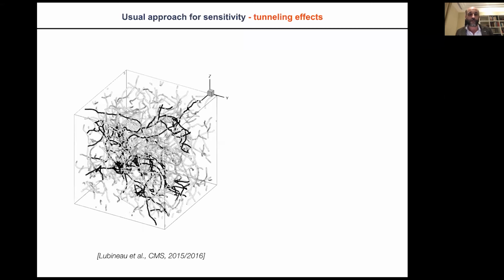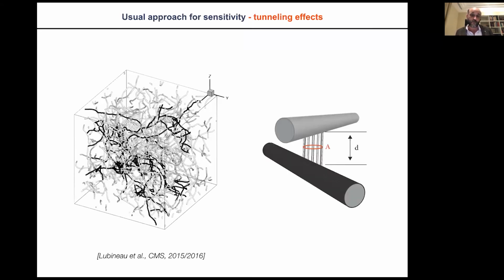So what you see in black here is a simulation of the percolated network of nanoparticles in a loaded polymer. It's impressive to see how many particles, in fact, are useless to the electrical signal, because all the white particles are not connected to the percolated clusters, so they don't conduct anything. The black skeleton here is the conducting network, and you know that the electron path between these different particles is realized by contact and tunneling between different nanoparticles, right? If you want to jump from one particle to another one, you have to jump through the tunnel here.